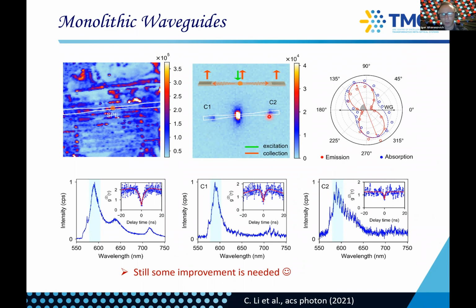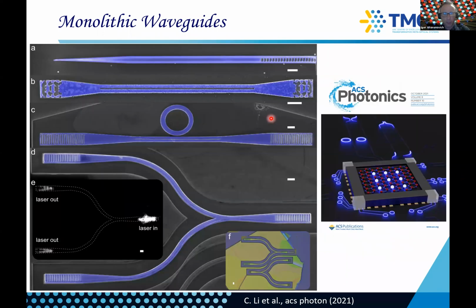You can see that the waveguide is not ideal. We have a lot of losses on this end. Also, the spikes here are the Fabry-Perot resonances from the light bouncing within the waveguide. So there is a little bit of improvement to do, but nevertheless, the proof of principle is done, and we can really expand this structure into coupled ring waveguides and tapered fibers with photonic crystal at the end.